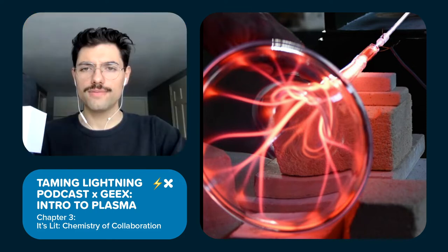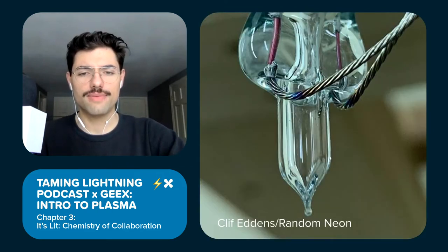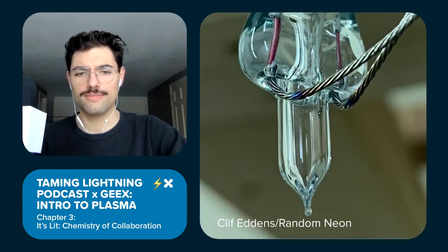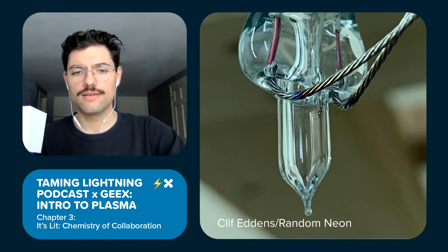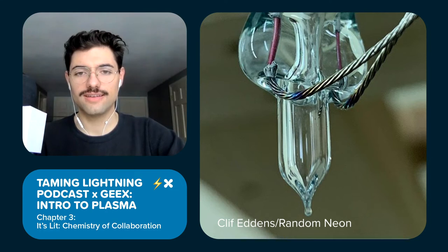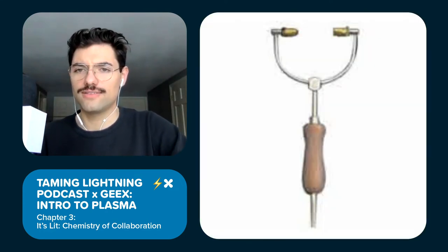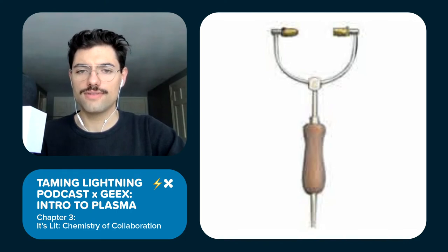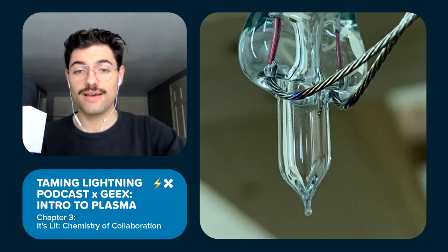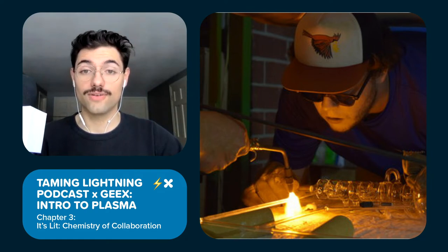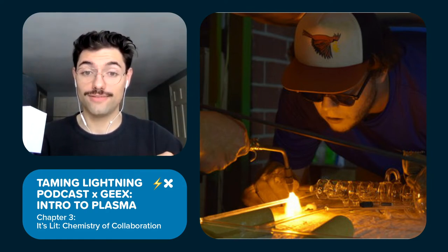And once we satisfy those requirements, let's tip off or remove the plasma vessel from the gas manifold or transfer system. So you'll want to have your hand torch ready and adjusted. I mentioned the use of neon hand torches in chapter 2 for this use when working with any sort of tubulation. But in particular, now would be a really good time to work with the tipping torch, which I mentioned, for soft glass. So you'll want to locate your ideal spot for tipping off the piece from the system. And remember that it's helpful to do the tip off twice, leaving yourself some room to make repairs or corrections once you initially remove your work from the manifold.